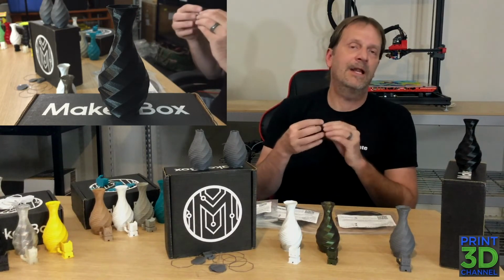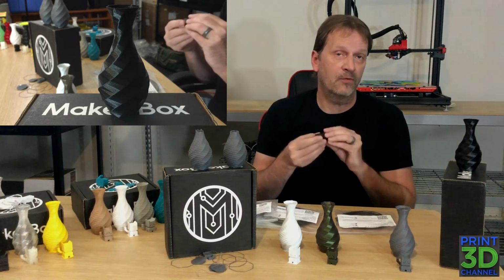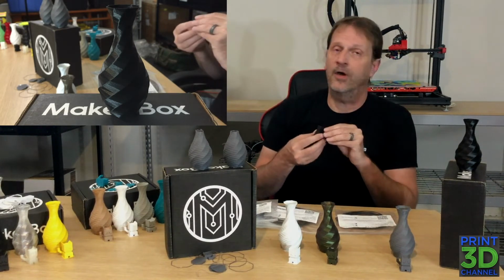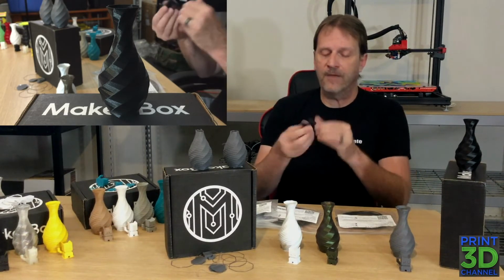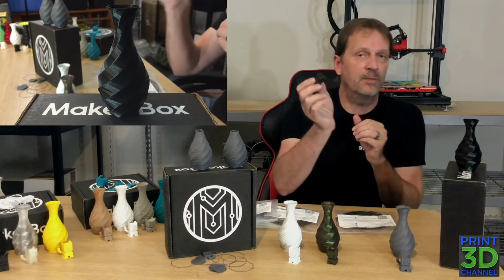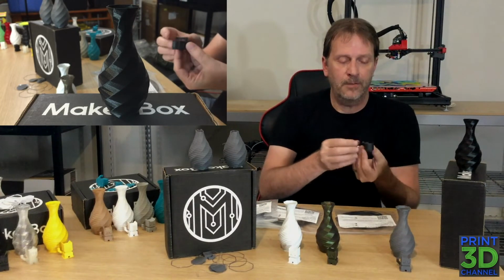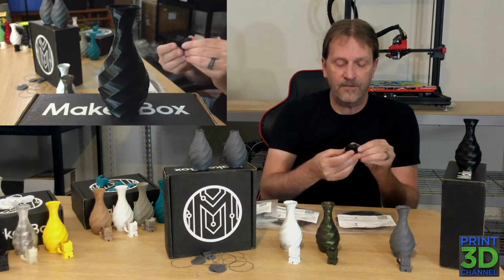Our speed that we printed it out at was 35 millimeters per second with no variables, and the speed recommendation was 40 to 100 millimeters per second. But I didn't have any problems with it. In fact, the bottom of it looks good. We did use a little bit of Magigoo for a bed assist, but the prints turned out really great. I'm super happy with the way this looks.